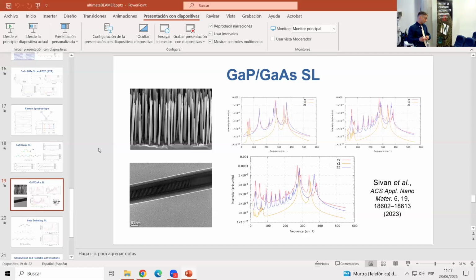Light carries a definite polarization. So you will have an incident polarization and a scattered polarization. Here I plotted the three non-equivalent polarization setups, because since our theories are symmetrical with respect to time reversal, if you take the YZ or ZY or whatever scattering configuration, you wouldn't see any difference. I only plotted double Y, YZ, and double Z because the X and Y directions are equivalent in this superlattice, because it's a wurtzite primitive cell, so the X and Y.